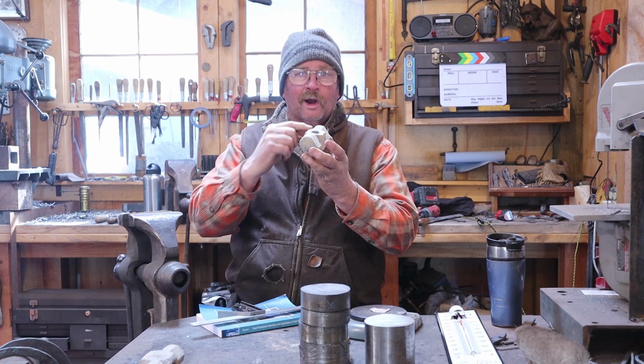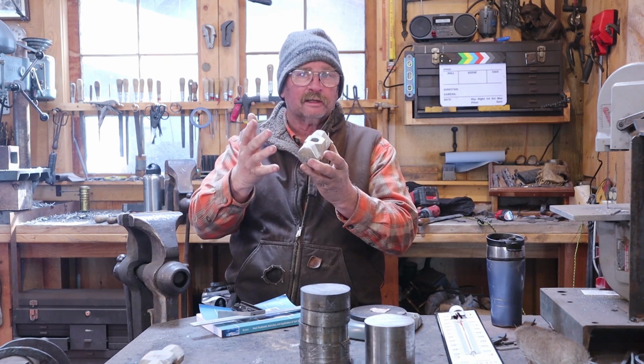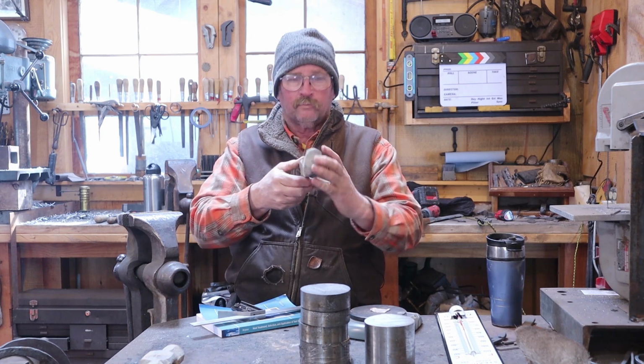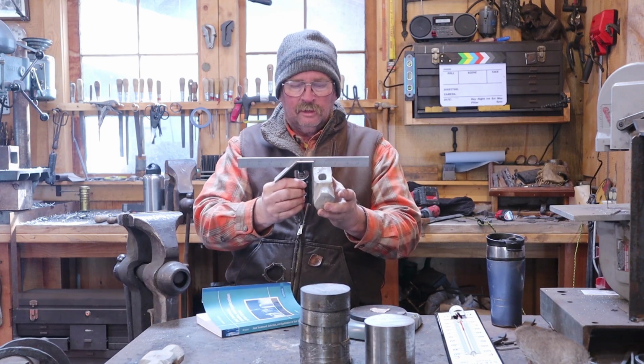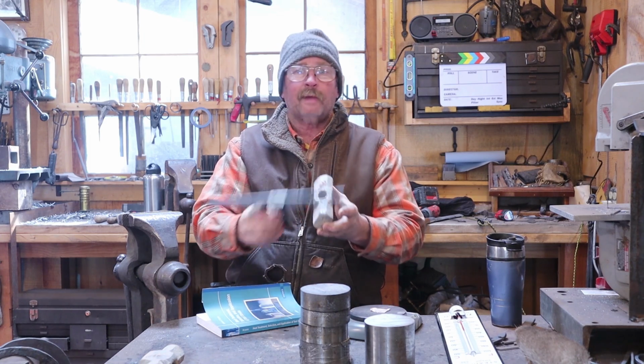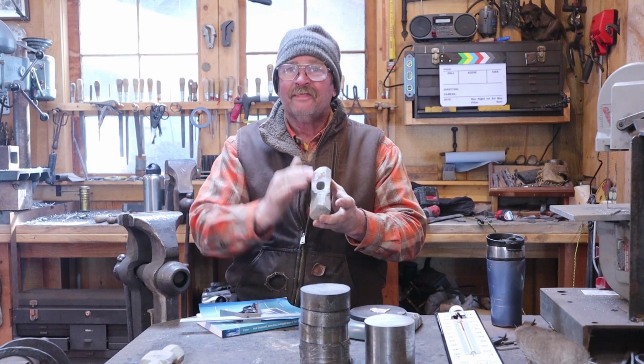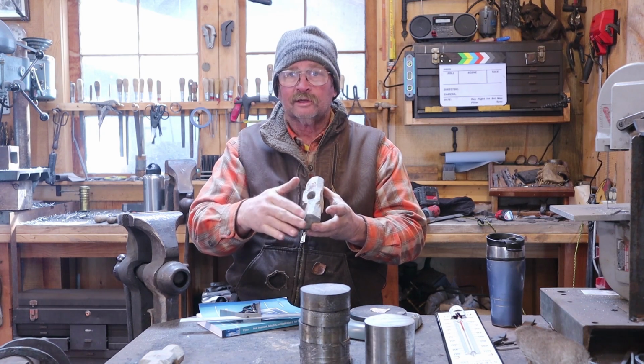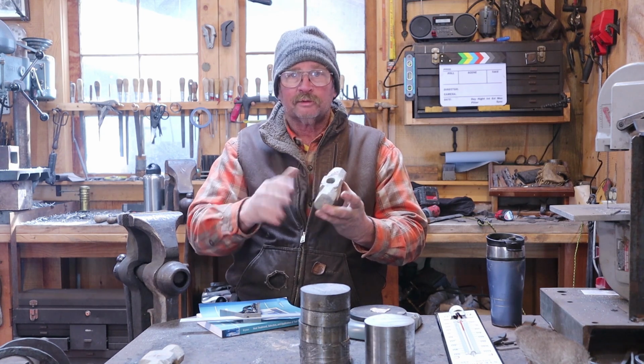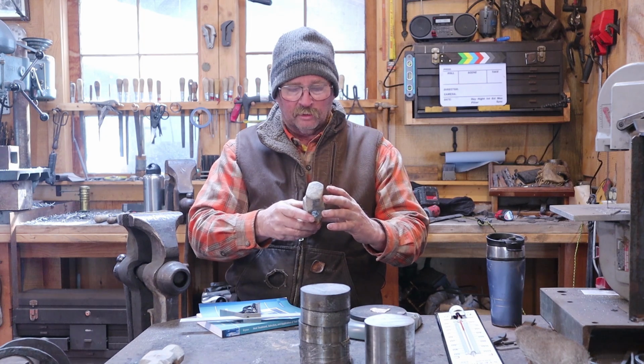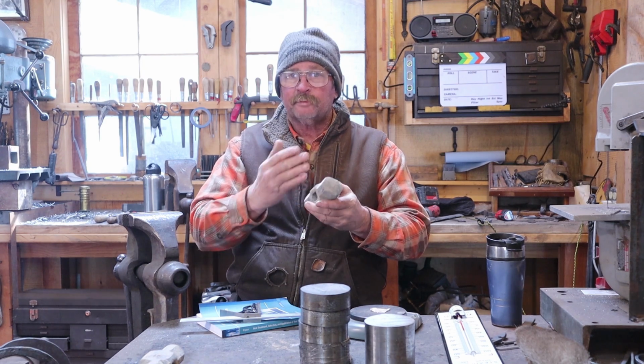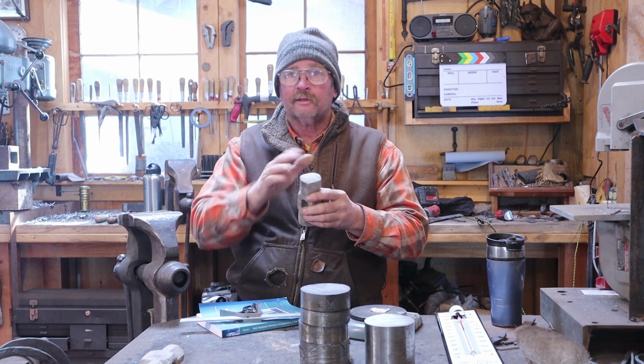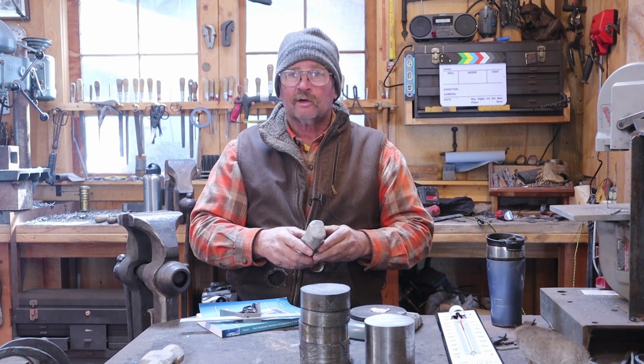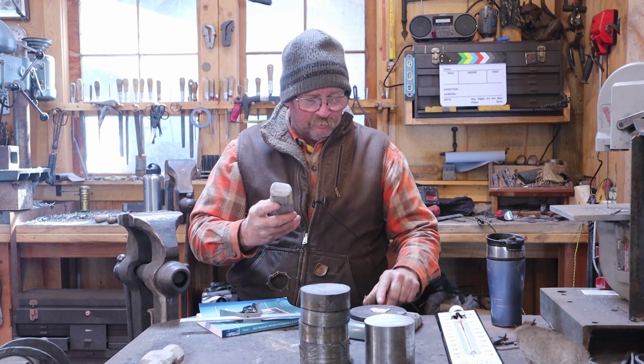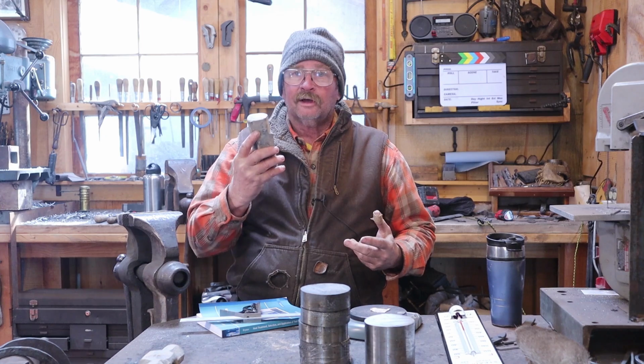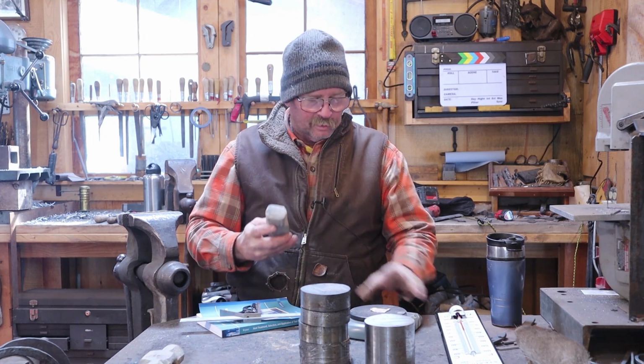So I think I can just grind the high side off the top. It'll take a little bit of weight off the hammer, which hopefully won't be too much. And both sides of the hammer are about the same square-wise. That'll square this up. It'll make it look good. It'll keep the eye running parallel with the sides. Shouldn't be any trouble at all. Then I'll clean up the peens and grind the profile on the peens and get that ready to go before we harden it.